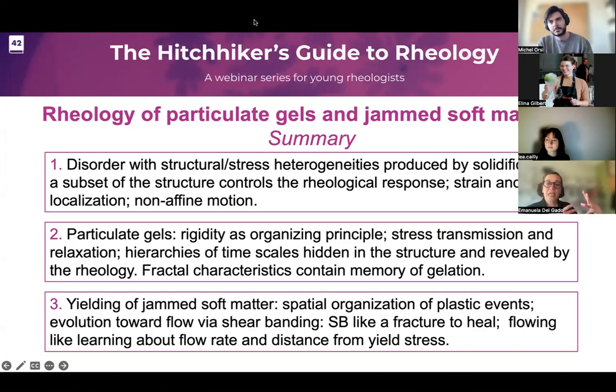So there is a lot of opportunity for the microscopic dynamics of the system to then enter and determine the response of the system. Whereas if I'm going too fast, it's just the deformation rate that will dominate everything. Most of my motion will be affine, and so I don't capture really what's happening in the experiments. So the thermal quasi-static shear was introduced to try to mimic the fact that the system is actually able to reach a local minimum before I continue shear.